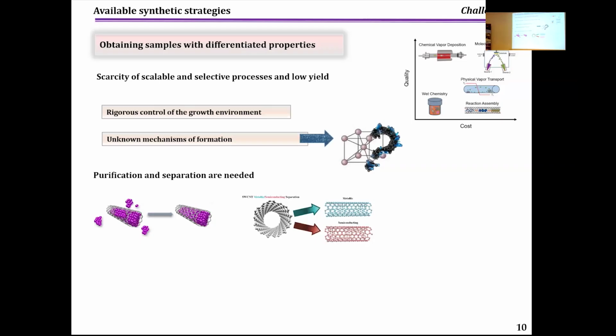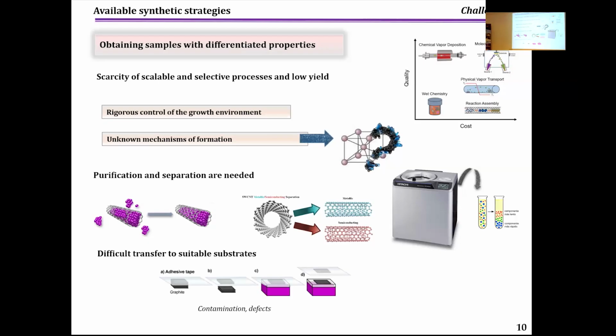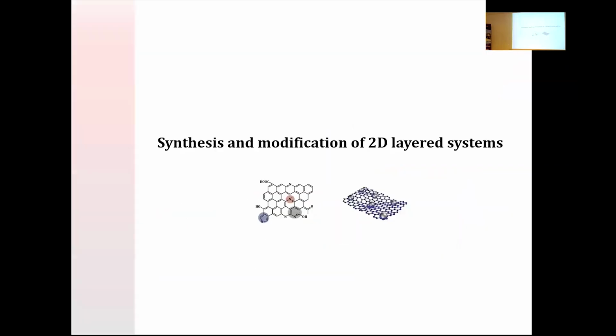And also, in some approaches, purification and separation are needed. There are some approaches that include ultracentrifugation that are sometimes reported to separate nanotubes with different properties or filling degree, but this is not very developed. And finally, in the case of exfoliation, there are difficulties in the transfer to suitable substrates, and contamination and defects are also an issue.